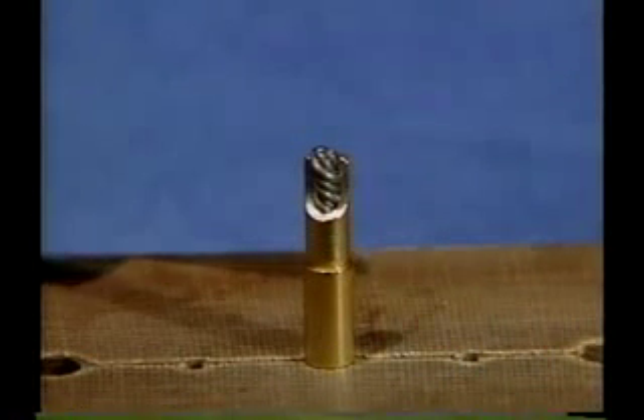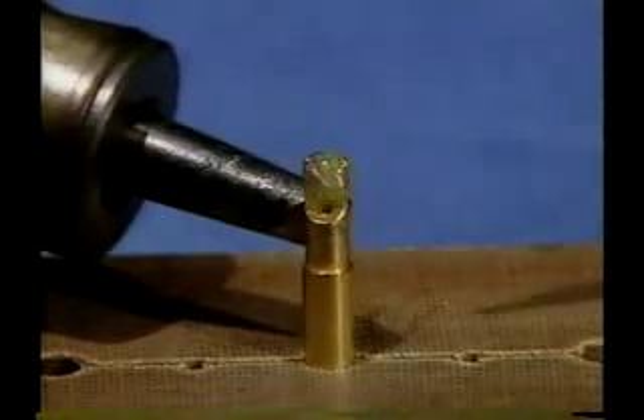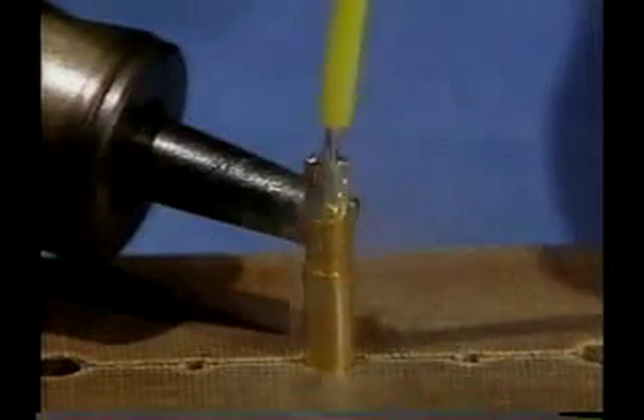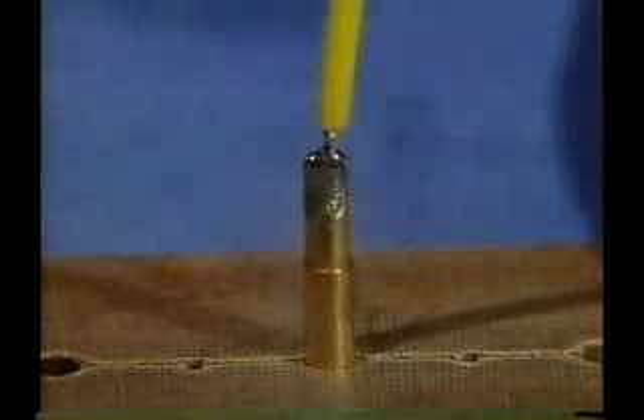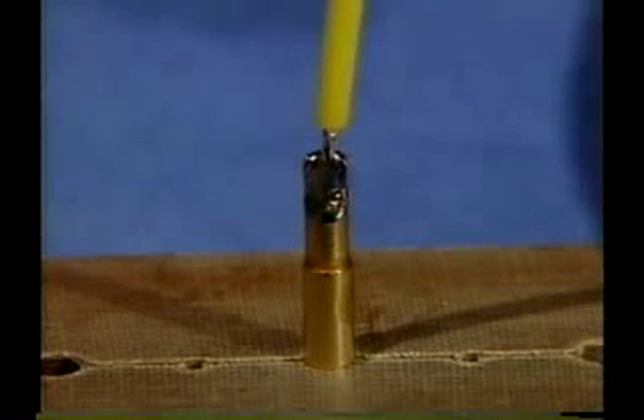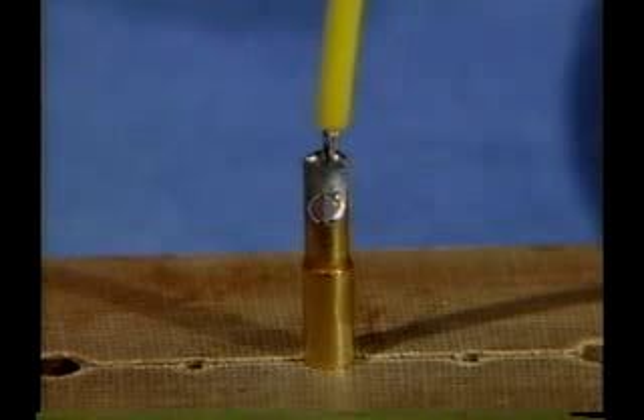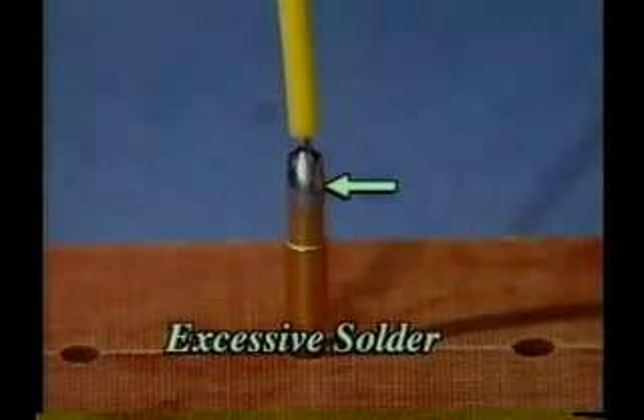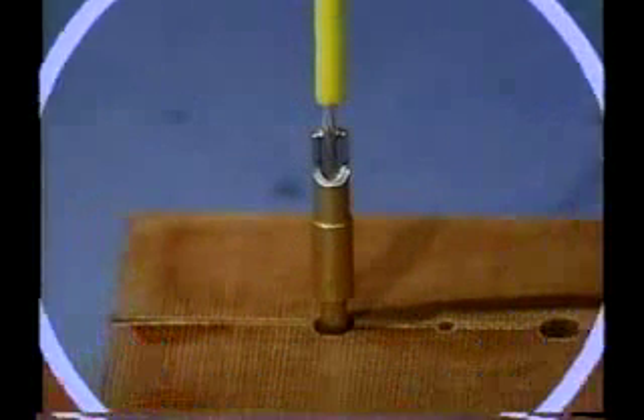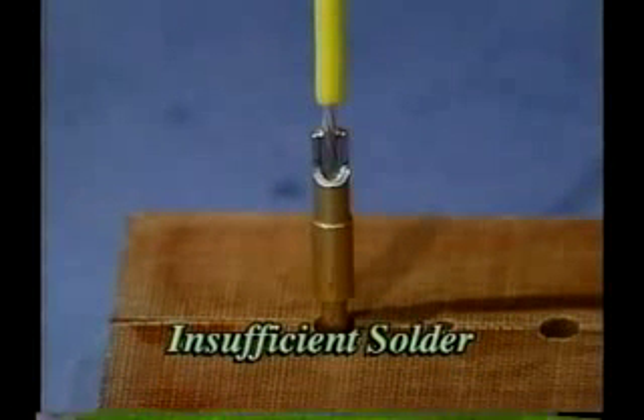Heat until solder flow is observed. Install and position the wire. Remove the iron and hold the wire in place until solder solidification. If excessive solder is used, it will spill down the sides of the cup. If insufficient solder is used, there won't be the minimum mechanical strength required.